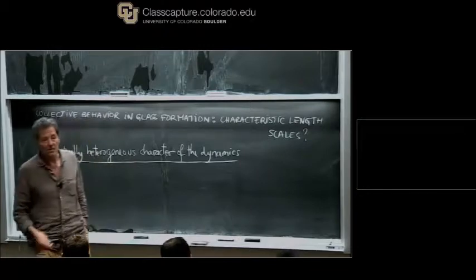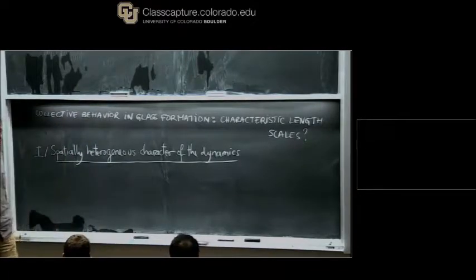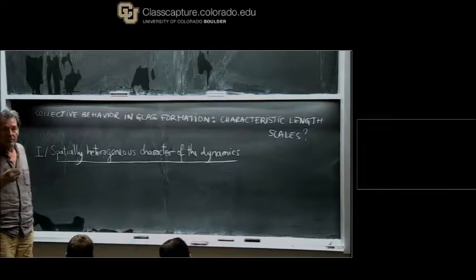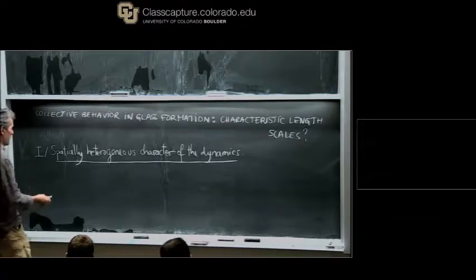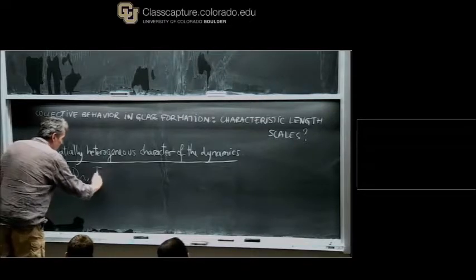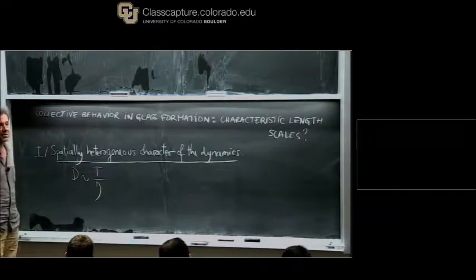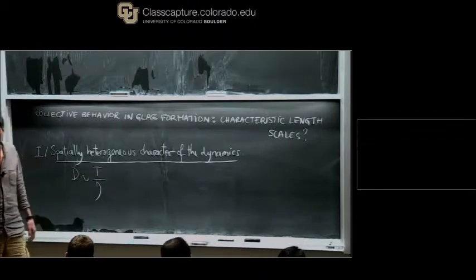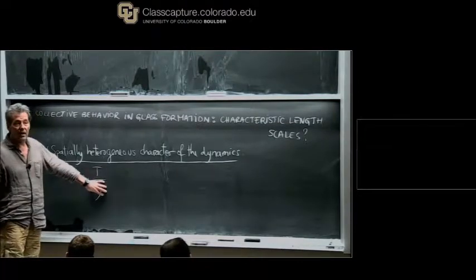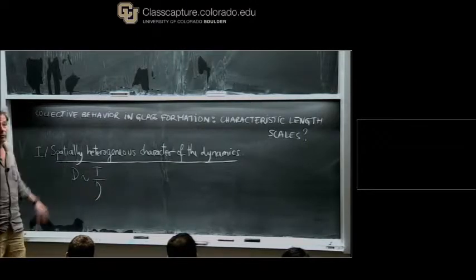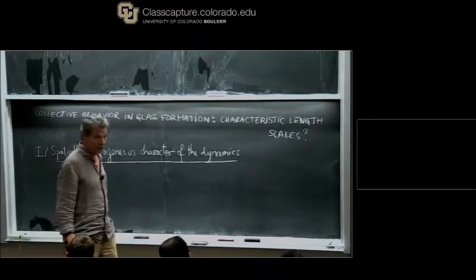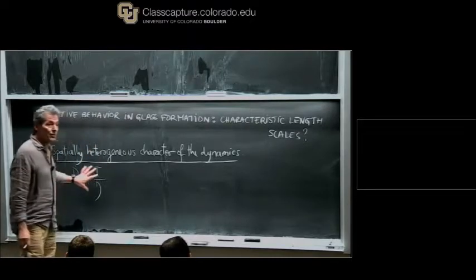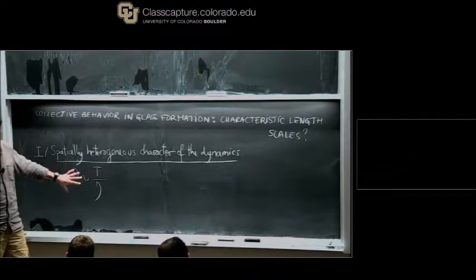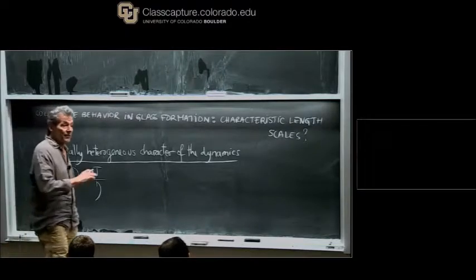What you have basically is diffusion motion, and a diffusion constant that you can measure. And the diffusion constant, by the Stokes-Einstein relation, goes something like temperature over viscosity. So you can say, okay, temperature changes by 30%, so no big deal. The viscosity changes by 15, 16 orders of magnitude, so one over D should just follow the same behavior. It turns out that it was measured in several molecular liquids and polymers, and you can see that, in fact, this is not true.